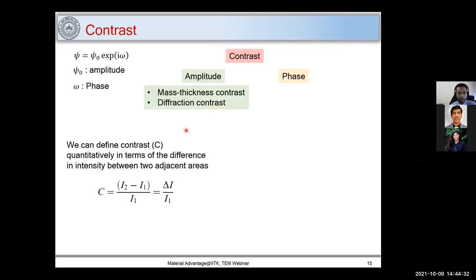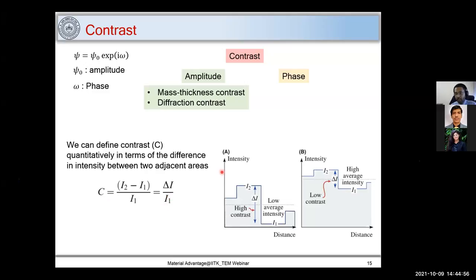When I talk about contrast, I'm talking about a difference in intensities. This has to be understood. Let's say I have two pixels adjacent to each other with intensities I2 and I1. I can find the difference between the intensities and normalize it with one of the pixel's intensity to get the contrast. So C is equal to delta I upon I1, and this contrast depends on the intensity also. If I have a higher intensity, I will have less contrast. If I have a lower intensity, I will have high contrast. And for your information, our eyes can tell the difference only if the contrast is more than 5%.